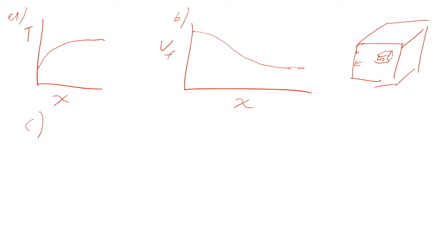All right, building on what he said, part C assumes the same behavior, except the interior is free to have some viscous flow while the surface is fixed. What ends up happening is that because the surface is fixed and you get some relaxation, you no longer have compressive stress, but because you have less free volume and everything's relaxing a bit, the interior is pulled to the surface.